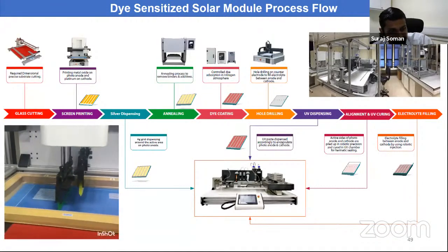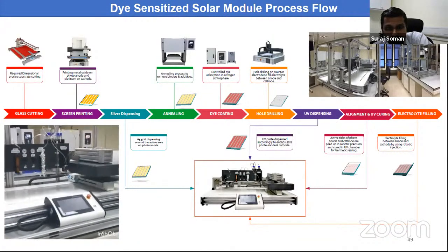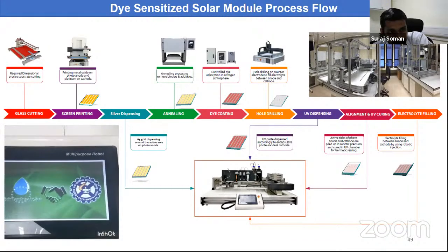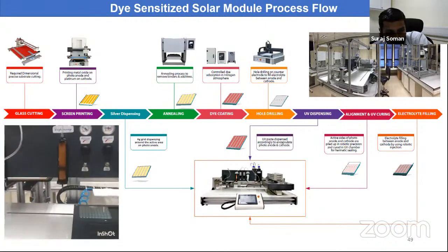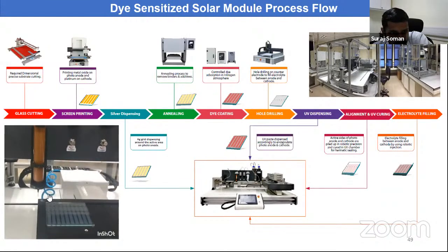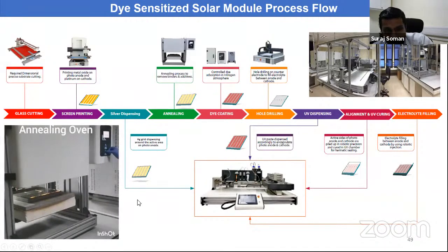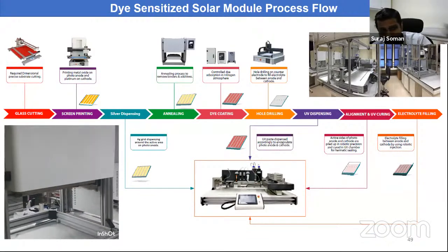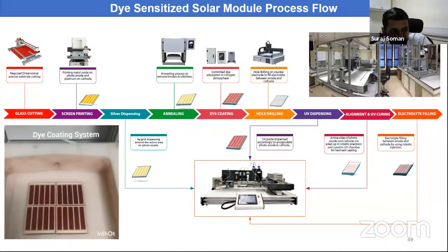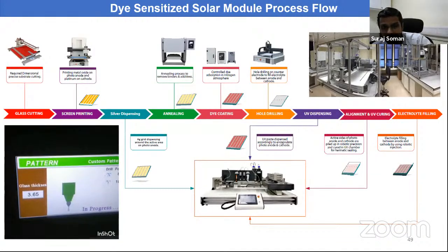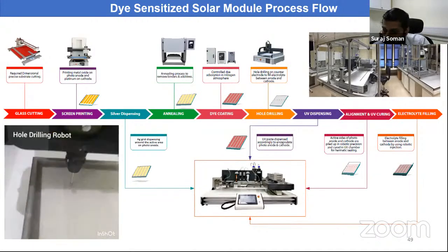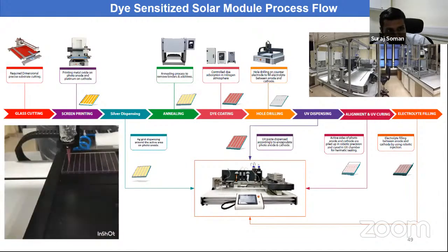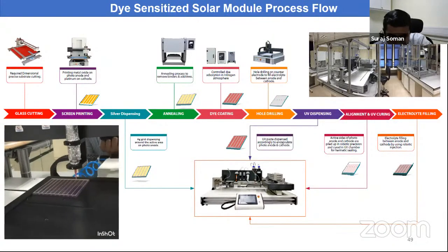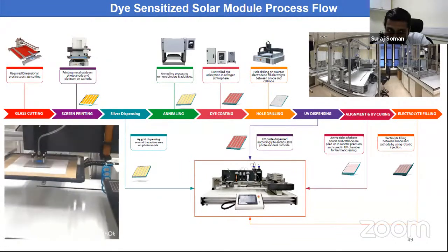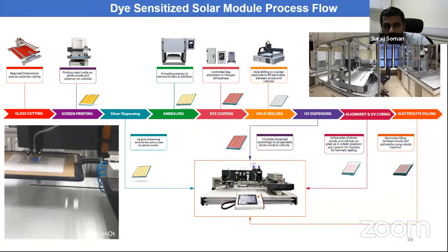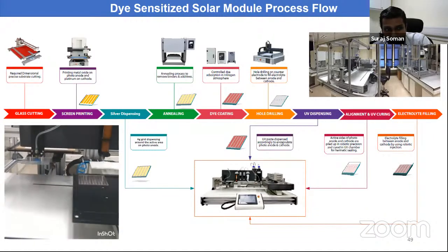Once the glass is cut, different designs are screen printed on the conductive glass electrodes. Then it is taken to the robotic system where there is a silver dispensing unit, which will dispense the silver lines in between your electrodes, and this is annealed so that the binders and those kinds of particles are removed, and then treated in a dye coating system in a nitrogen atmosphere. The dye absorption is carried out. Then on the counter electrodes, holes are drilled, and then these are sealed using a UV epoxy. The epoxy is coated onto the silver lines because they need to be protected from the electrolyte.